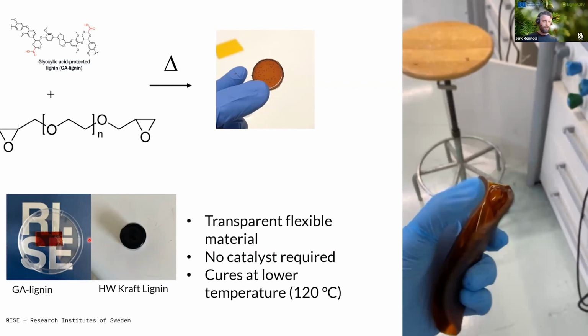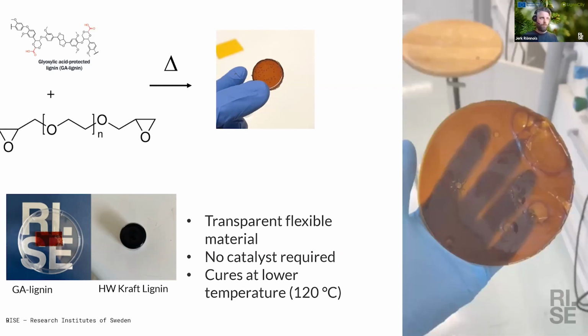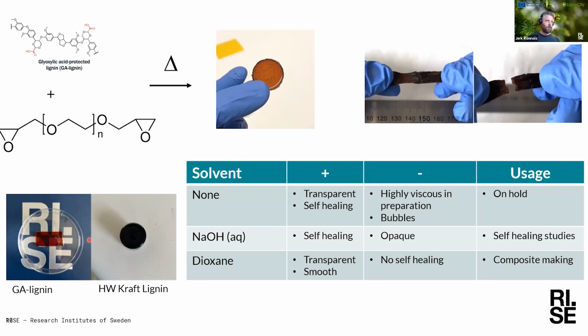So that was very nice. We tried out a few different ways of formulating this, including exploring some solvent options. We did explore more than these, but these are the ones which we are continuing with. Without using solvent, just mixing the reagents, the lignin and the crosslinker, we got something transparent, which was self-healing to some extent as well. And that was on the plus side. But on the minus side, it was highly viscous in preparation and difficult to disperse properly. And we also got these bubbles, as you can see in this one. So this is put on hold for the time being, maybe revisited later.